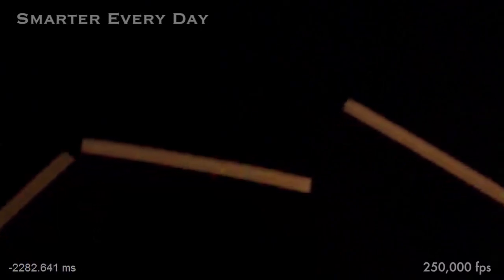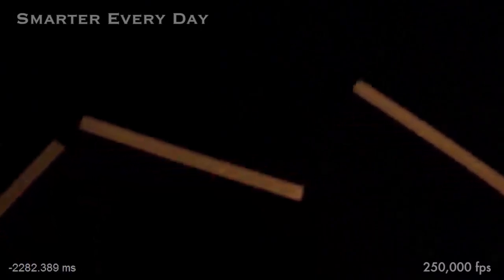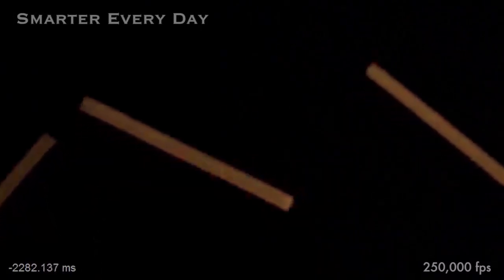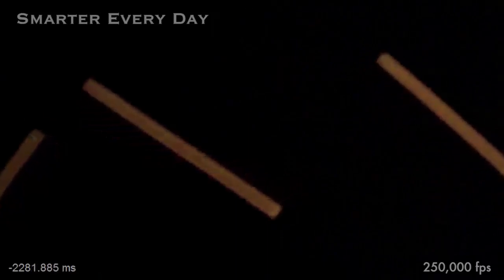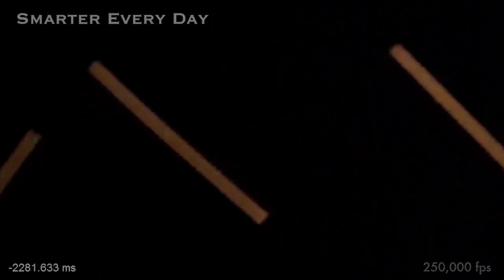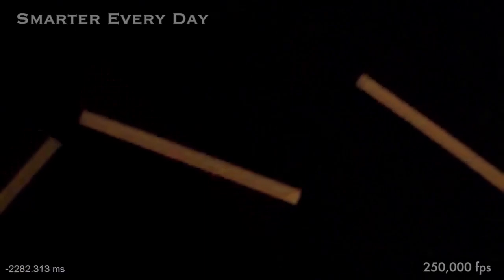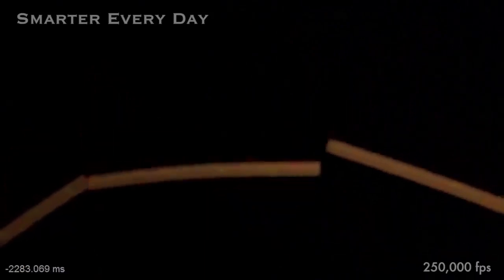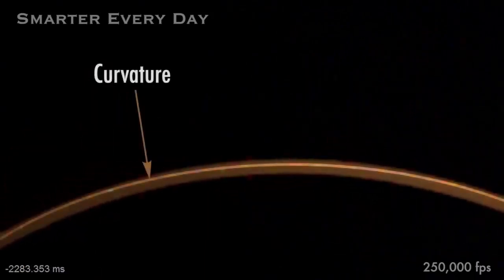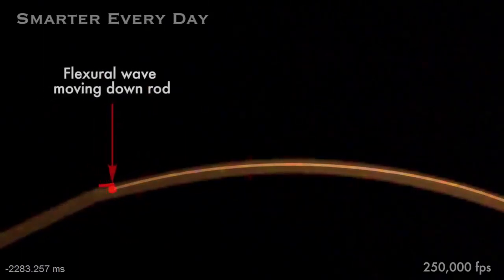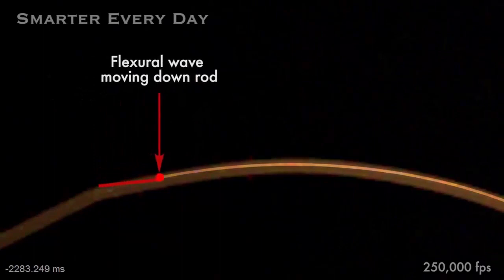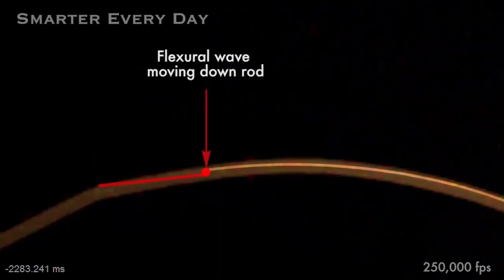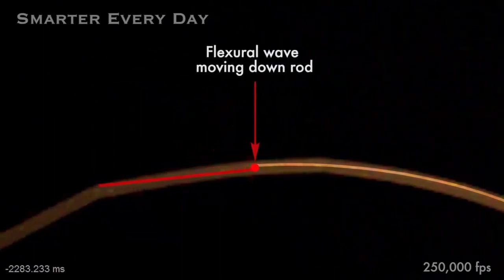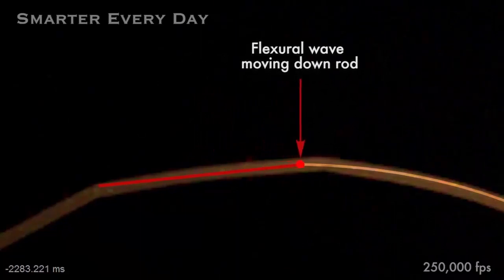Man, we had to go way faster than I thought we would to get this answer, but there it is. I mean, it's not vibration. It's the curvature of the spaghetti as it straightens out. Think about it this way. The entire spaghetti rod is under torque, right? Because of this torque, it bends in a curve. And when a break occurs, the side near the break is now free from torque. But there's still this counter torque built up in the rod. So it starts to straighten itself out from left to right, rotating up and straightening out along the way.